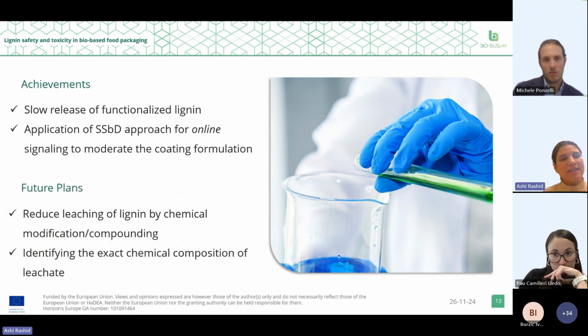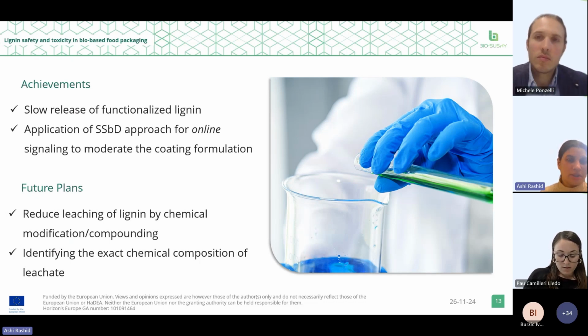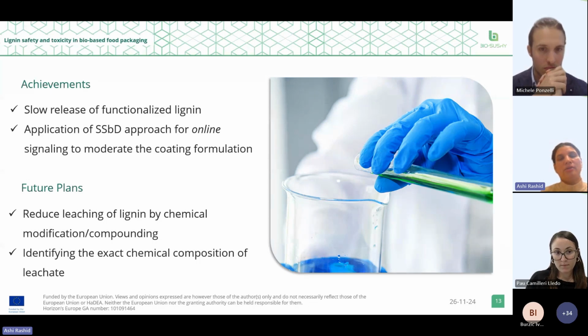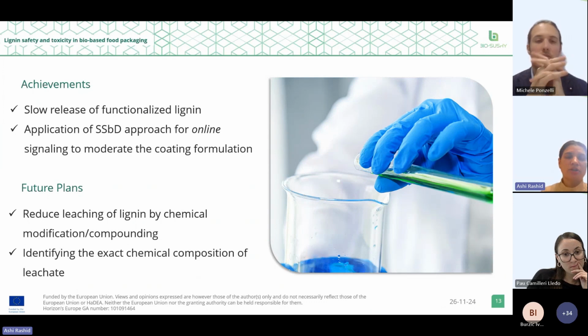From our data, we can say that lignin is released, so we have successfully applied the SSbD approach for online signaling to moderate the coating formulation. We can also see there is successful modification of the lignin surface, which resulted in the slow release of the functionalized lignin. This could be further reduced by either modifying the functionality on the surface of lignin, or by compounding the lignin with other thermoplastic polymers to reduce the amount leached.